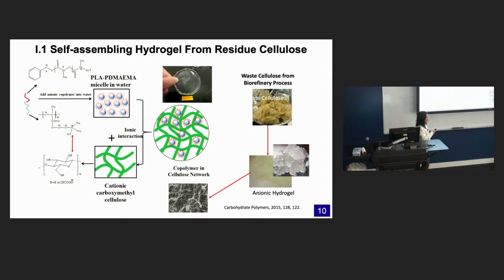The method we use is to remove the lignin through delignification, but we don't cut the cellulose length too much, so we can form the nanofiber. We believe that, and we have data showing that the hydrogel has better strength. This is some work we published a long time ago. We made a hydrogel with high strength, and we also used PLA and PDMAEMA, depending on the different molecular structures. PLA is the harder part, PDMAEMA is the softer part.